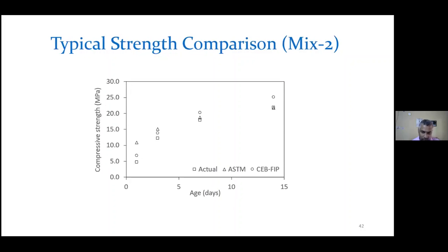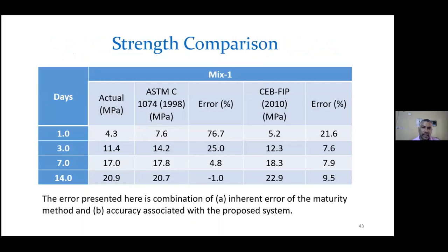For the 5 mixes we got almost similar types of results. For one mix, I have shown you in detail the type of error that we got, and for the other mixes we got similar results. And here we can see the error is a little high for ASTM in the very early ages, but as it gets close to 14 days, the error reduces, right? And CEB-FIP gives you different results. Here the errors are comparatively low, but here errors are higher than ASTM.